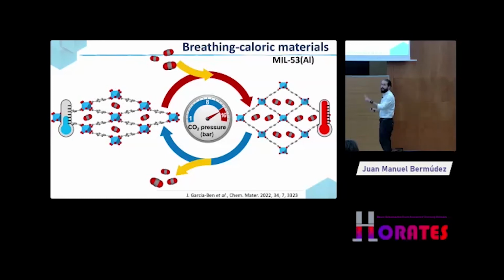First, you have the solid-to-solid phase transition, the contribution of the lattice. So there is a lattice that is changing the phase, okay? So this is one contribution. And then you have another contribution, and it is the adsorption-desorption of the CO2 in the framework, which is interacting with the framework, creating hydrogen bonds. So you have two main contributions here, solid-to-solid phase transition, which will be equivalent to the barocaloric effect, and absorption-desorption process, which will be equivalent to the absorption-refrigeration systems. And both contributions add on, and then you end up with a given value for the isothermal entropy change, okay?